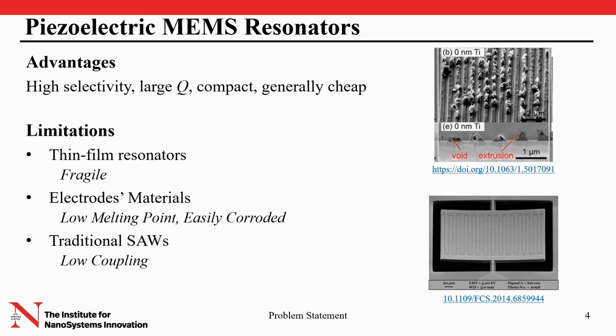For this reason, piezoelectric MEMS resonators are an ideal candidate as they present overall good performances. They're generally compact and cheap. However, they usually have limitations. Especially thin film resonators are fragile, and it's not a good idea to employ them as suspended structures in contact with hot viscous fluids. Additionally, electrode materials such as aluminum, which is very commonly used in SAWs and LVRs, have low melting points, are easily corroded, do not handle power very well and suffer from electromigration, as we can see in the top right. Finally, traditional SAWs have low coupling, which ultimately limits their applicability.